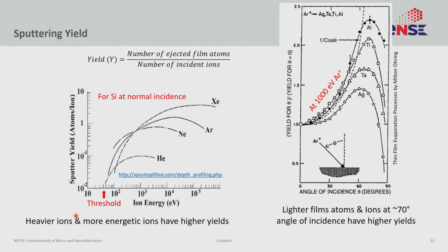Let's first talk about sputtering yield. Sputtering yield, very simply speaking, tells you that for every atom of argon or every ion of argon that is bombarding the surface, how many atoms of the target material are actually coming out, all right? So a sputtering yield of 1 means for every atom of argon plus, 1 atom of the target comes out.